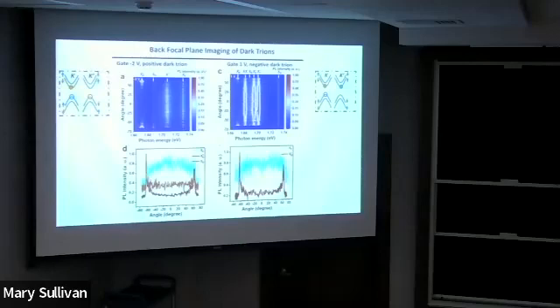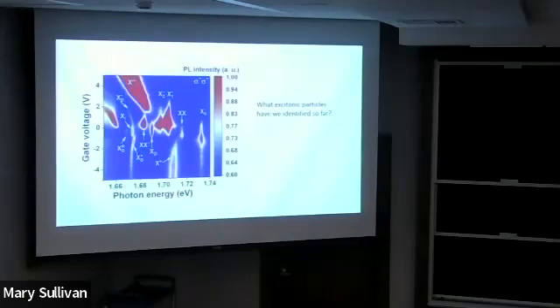One nice thing about this, probably I don't have time to elaborate here, but dark exciton is very nice. It's long-lived compared to the exciton. But according to our discussion, this one is linearly polarized and does not have a valley degree of freedom. Right? You were able to increase lifetime, but you lost the valley degree of freedom. Dark trion also has a long lifetime, but it has a finite valley degree of freedom. So here in this plot, we've identified most of the peaks. This is the exciton, charged exciton, dark exciton. This is the plasma mode. I'm not going to discuss it today.